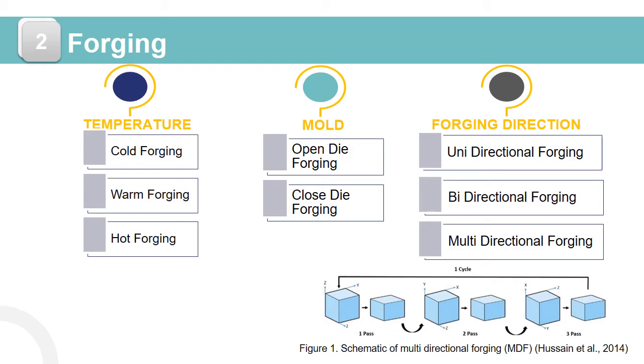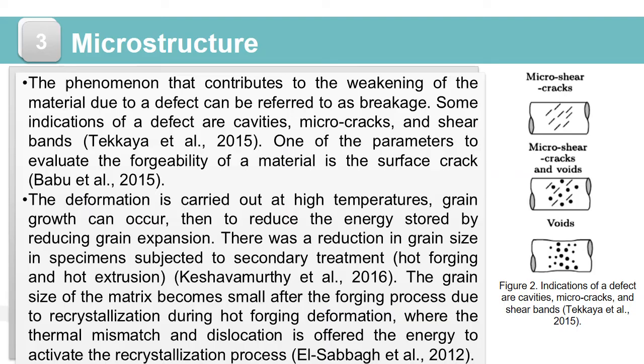Multidirectional forging is a technique in which the sample is pressed in a channel die to a fixed strain, removed, rotated by 90 degrees, reinserted in the channel die, and pressed to the same strain. This is repeated in three orthogonal directions. Kavosi et al. found that increasing the pass number of multidirectional forging increases the strength and dislocation density of the alloy. The multidirectional forging scheme is shown in figure 1.